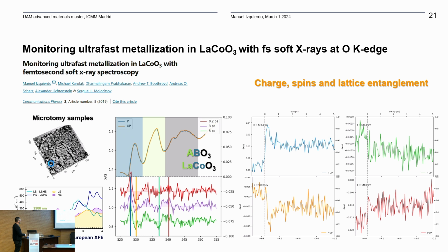If you look, there are modifications in all the oxygen K edge. So it means that we have changes in the electronic and the spins. You have changes also in the interaction with the lanthanum, and then you also have modifications of the structure, which indicates something that we have observed before, that the charge, the spin, and the lattice in these compounds are entangled, and this entanglement happens on the femtosecond time scale, because you can see here in the time traces that there is a fast response of the system upon photoexcitation.